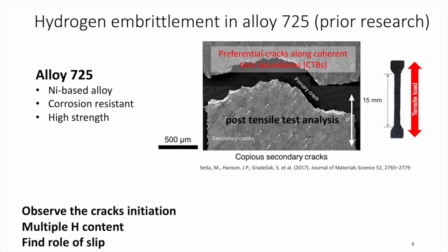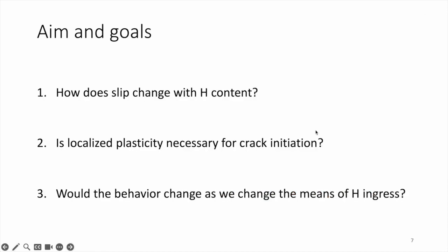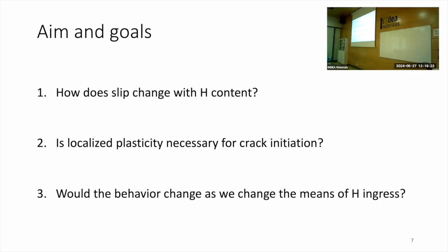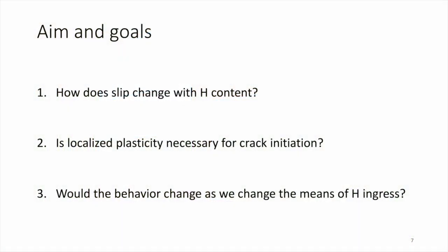To achieve these goals, we need to conduct experiment in situ inside of the SEM and observe the changes while they are happening. So today I'm going to talk about three things. The first is, how does the slip change with hydrogen content? The second thing is, is localized plasticity really necessary for our crack initiation? The third thing is, remember we talked about hydrogen could come from different ways, right? It could be from the cathodic side, or it could be from the environment, gaseous environment. Would the behavior change as we change the means of hydrogen ingress?